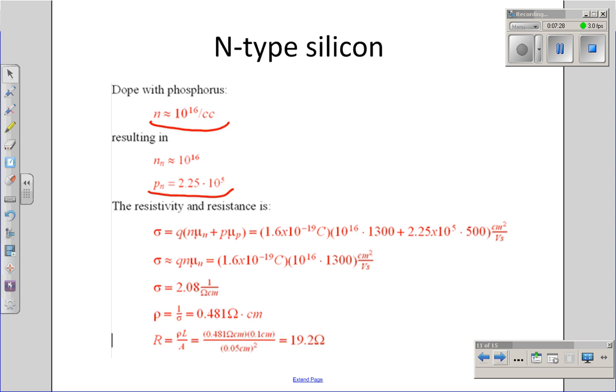Again, using the same calculations as before, if I dope the silicon with 10 to the 16th atoms of phosphorus per cubic centimeter, the resistivity drops to 0.481, and the resistance is 19.2 ohms. If you recall, for p-type material, the resistance was 50 ohms. N-type material with the same doping was 19 ohms. N-type material has slightly less resistance than p-type material. That doesn't really matter, however, because you can adjust for that just by changing the doping concentrations.